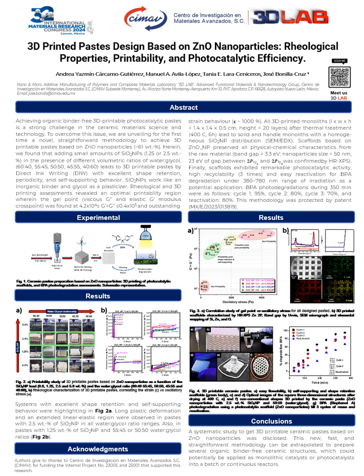In the strain versus stress curves, we can observe that those of 5% do not have resistance to deformation, which resulted in hard pastes that dried quickly and could not print their ink. Those of 2.5% have that plasticity, there is elongation. This resulted in fluid pastes, with plasticity and excellent for printing, as well as the curves of 1.25%, but only those of 55-45 and 50-50 presented the same behavior as those of 2.5%. Those that did not have silicon oxide, that is, 0%, were liquid and could not retain each other,